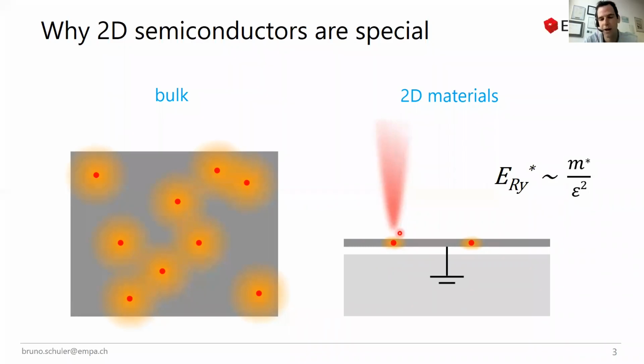So typically, most of the defects in 2D materials are deep defects, and their binding energies are on the order of a few hundreds of milli-electron volts. So about a factor of 100 bigger than in bulk semiconductors. And this bigger characteristic energy scale is also the reason why quantum properties are visible, even at elevated temperature, and they're fairly robust.